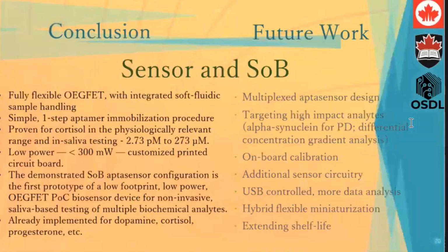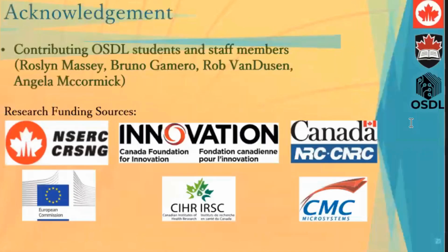So to conclude, I've demonstrated a fully flexible OEGFET with integrated soft fluidic sample handling, which has been extended to multiplex aptasensor design. The variability is minimal as long as the deposition step is consistent. Interfacing is to a system on board right now. We are incorporating onboard calibration and hoping to go towards hybrid flexible miniaturization. Extending the shelf life is in the works, and implementing it for future targets. Our current work is looking at alpha-synuclein for Parkinson's detection. So a little more high impact perhaps than continuous monitoring, of course.